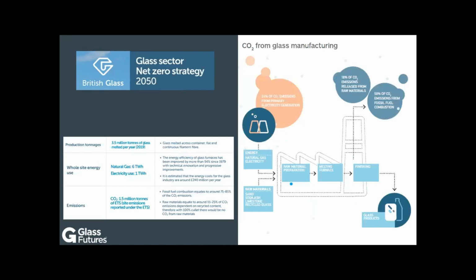So glass itself is a very energy intensive process. Obviously, you've got to melt the raw materials. The primary raw materials are sand, limestone, and sodium carbonate. You mix those together with some other additives and hopefully a lot of recycled glass. You have to heat them up to around 1500 to 1600 degrees in the furnace to get them to melt and dissolve together. Then they come out at the end and you can form it into the final products. All that uses a huge amount of energy, as well as carbon dioxide generated from the predominantly natural gas that they use in the furnaces.